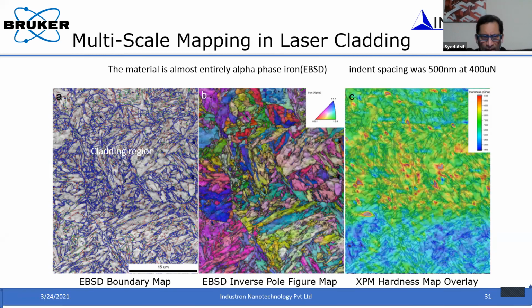The first map I'm showing is the EBSD boundary map. It shows you the high angle boundaries, and you can see the cladding region has a lot of high angle boundaries. And then the EBSD IPF map shows you the crystallographic orientation. Now, if you look at the hardness map in comparison with the boundary map, you can pretty much see how the hardness is changing along the grain boundary. We can do the same resolution as you do for an EBSD map; we can do this hardness map with this technique.